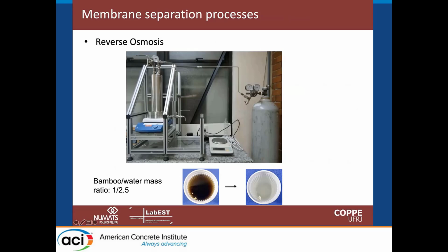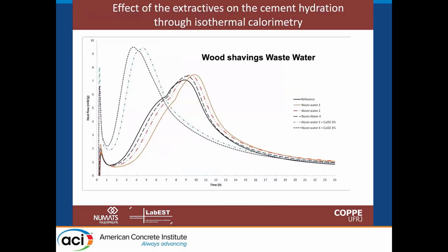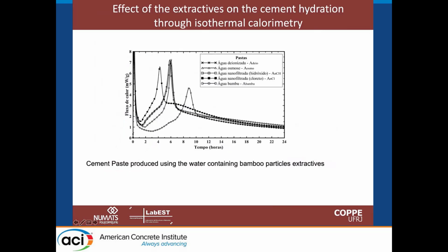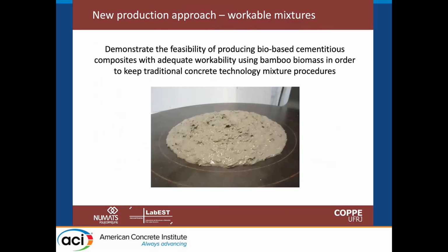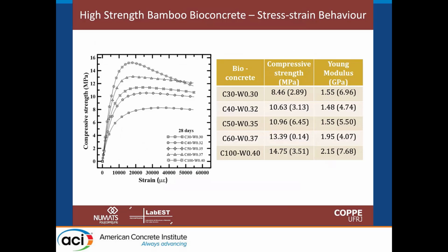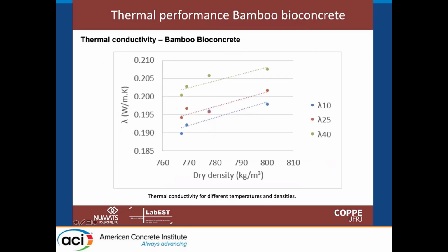And if we don't do that, we have quite a retardation, as we can see in these calorimetric results here. If this is just Portland cement, when we put the biomass without treatment, we retard it. But if we do osmosis treatment, even in some cases we come back to the same heat of release and the same rate as well. So these materials have nice workability. They can have compressive strength in the range of 15 MPa and very low density. These are materials that can have between 700 and 800 kilograms per cubic meter with low thermal conductivity.